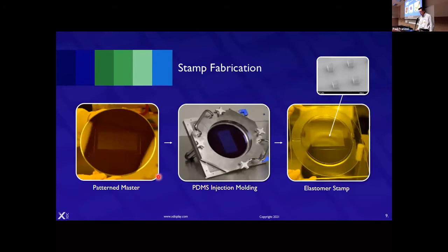So what we do is we make a master wafer on a silicon wafer. This master wafer has the inverse pattern of the stamp that you want to create. That wafer goes into a mold, and then you inject PDMS in between the glass plate and this master wafer, and after you cure the PDMS, you pull the stamp out, and what you have is a stamp that looks and feels like a photomask. It's rigid, but it has that compliant PDMS surface. If you put it in an SEM, you'll see the posts that are designed to pick up the individual microLEDs